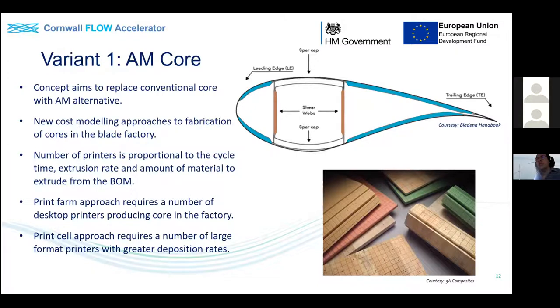So conventionally, these cores are made from slab stock foam materials, and they're often cut and scored because they're rigid materials. So they have to be cut and kerfed to basically allow conformance to a compound curvature. As you can appreciate in the figure, an aerodynamic blade shape that's changing through the Z-axis or through the page is a complex surface. And in order to get intimate mating with that, these cuts are necessary. In addition, these core kits, which come pre-assembled from the manufacturer, are quite a value-added good already, because in addition to those kerfs for conformance to a mould, they also need to be drilled. So it allows a path for volatiles, air and liquid resin to flow as part of the resin infusion manufacturing process. So it has a number of distinct disadvantages which we see can be overcome by using additive manufacturing.